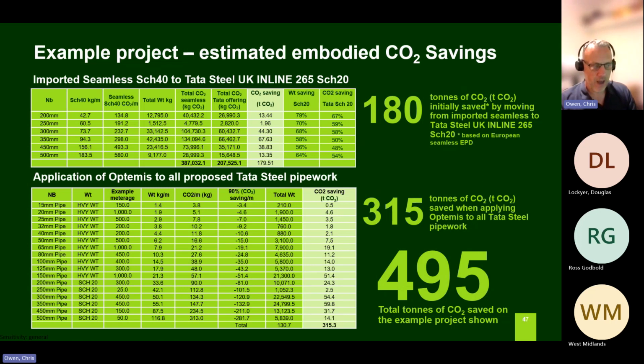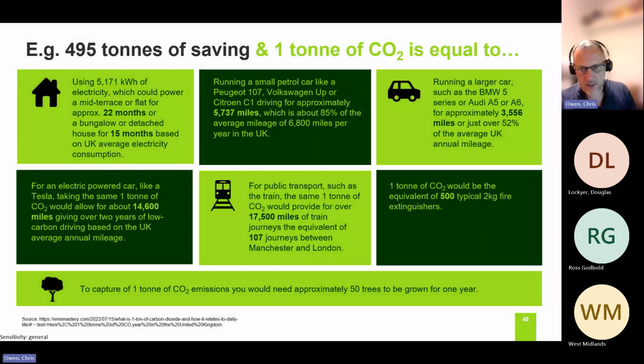We then applied the Optimus on top of the existing pipework, and that gave us a total saving of over 500 tons of CO2. And that's now a project which is in London, which is now looking at applying the same on other floors. So actually the CO2 saving is going to be even bigger. And when you start getting into the statistics about the CO2, and you see how much 1 ton of CO2 is equal to, then you can see that this is something which I think building services can really bring to the party. You know, the end client wasn't aware that he could achieve so much CO2 reduction through the pipework within the building services.